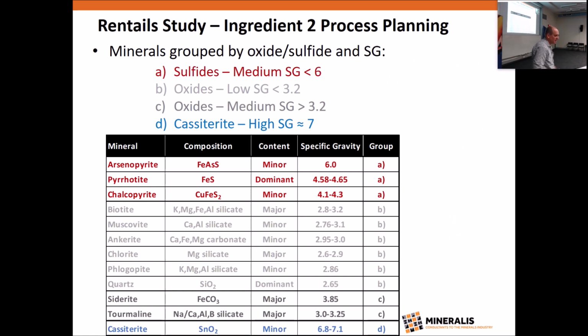So once we had a good understanding of the characteristics and the mineralogy, we set about planning the process. And the liberation data gave us a target grind size, which I think was about 53 microns. But then we grouped the minerals as sulfides or oxides, and then within an SG range. The objective was to form groups of minerals that could be expected to behave similarly in any part of the process. So we had the Group A sulfides, which are all pretty heavy, I think the heaviest was arsenopyrite, or at least medium SG. Group B had the light oxides with an SG below 3.2, Group C oxides with a medium SG, and we gave cassiterite its own group because it was special, Group D.